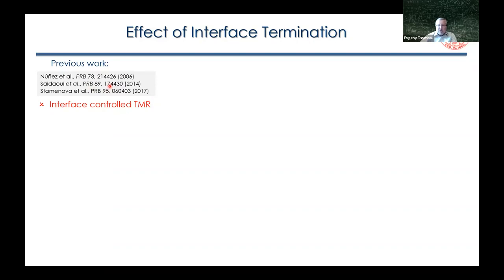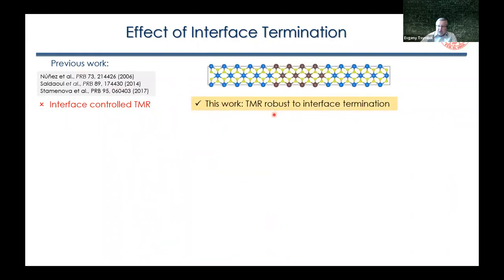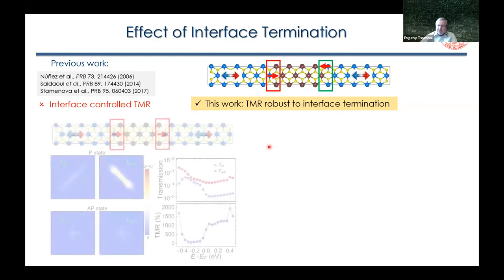In practice, however, we know that we always have interface roughness, and it's very hard to have uncompensated magnetic moment at the interface. So it's quite unlikely that this kind of antiferromagnet can be used to realize a sizable TMR effect in realistic experimental conditions. So this is not the case for our tunnel junction. We find that TMR is robust to interface termination because it's controlled by the bulk properties of antiferromagnets. So what I'm showing here is the original configuration we used, I've shown before. We have parallel aligned Néel vectors, and this is the termination we use. You see that for parallel aligned Néel vectors, the terminations were such that the magnetic moments at the interfaces were anti-parallel. So now let us change it.